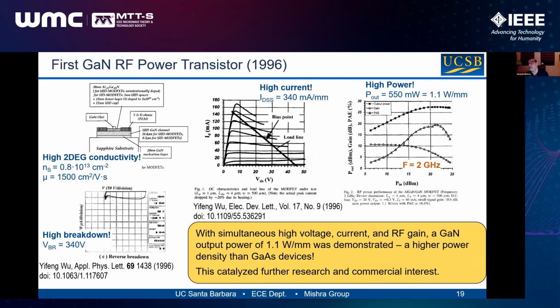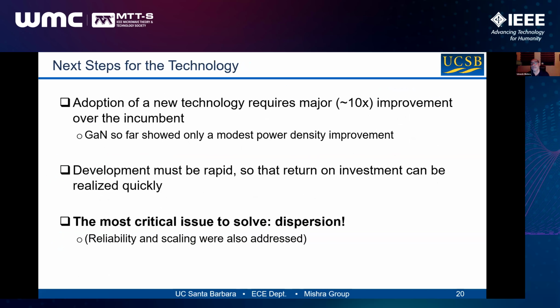Then what we did was, we basically decided to start doing the microwave power applications of gallium nitride. We thought that the only way gallium nitride is going to get any notice is if we went into the power applications, because we could get current and voltage at the same time. And we did our first demonstration by Yifeng Wu. We got 1.1 watt per millimeter, 1996, and that was as good as gallium arsenide production. So our first transistor met gallium arsenide kind of numbers. In fact, it beat it. So that was when we realized we were onto something serious.